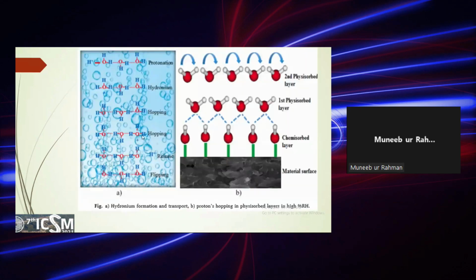This is the conduction mechanism, how the conduction takes place from one electrode to another electrode. This is the same image of the surface of that material on which this cartoon shows how the water molecules are adsorbed on the surface of this material. The first layer, which we call the chemisorbed layer, is chemically adsorbed on the surface of the material, and this first layer of water molecules is less mobile as compared to the second and subsequent layers above it, because it is chemically bonded with the surface of the material.